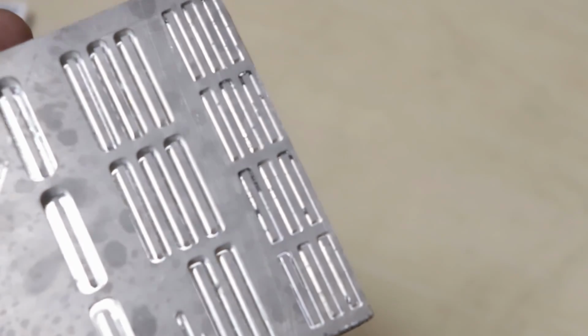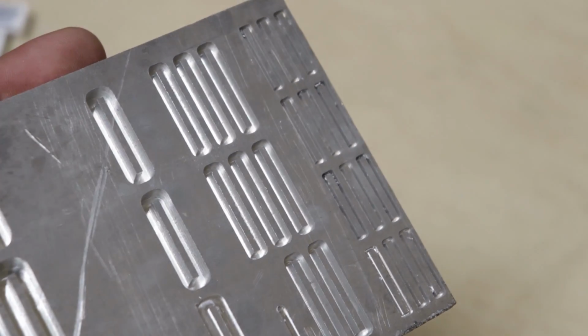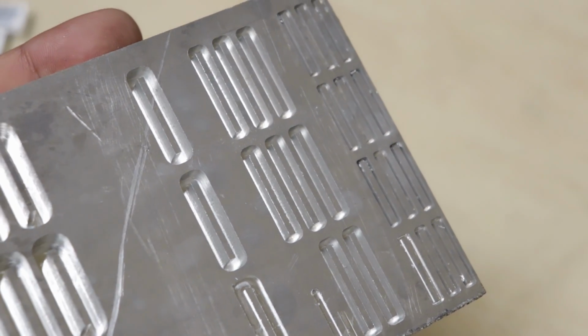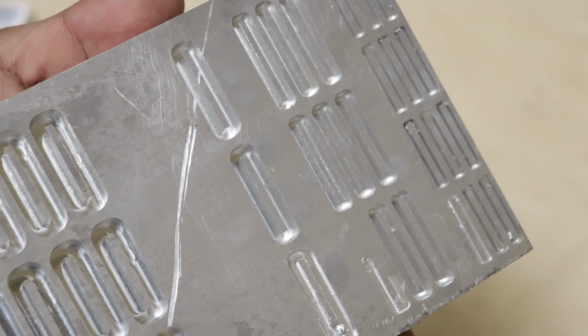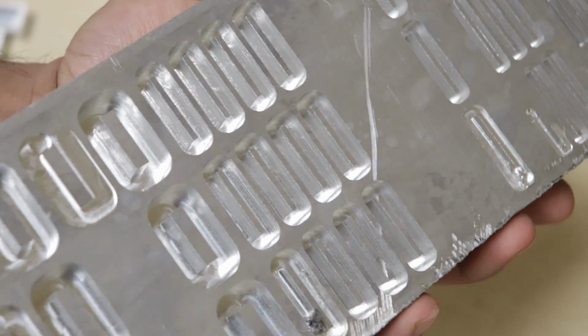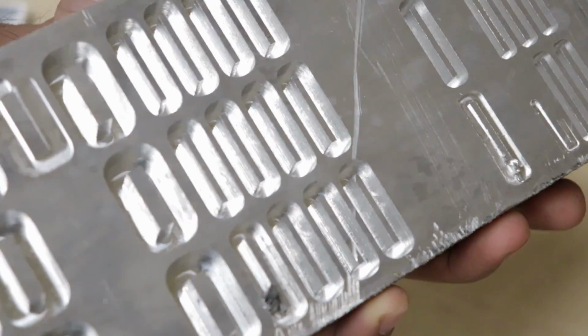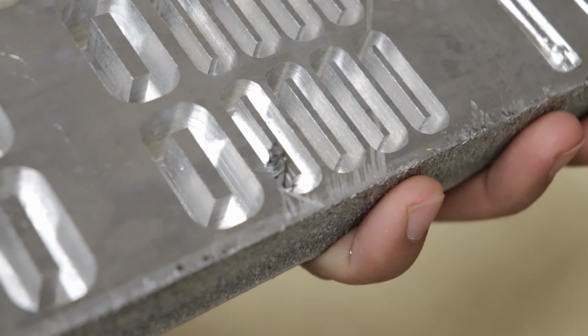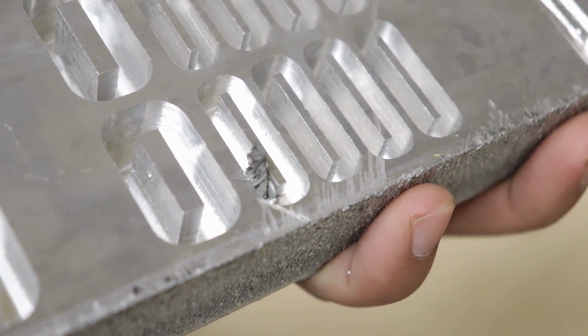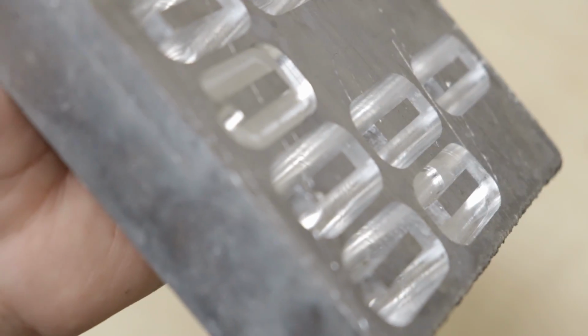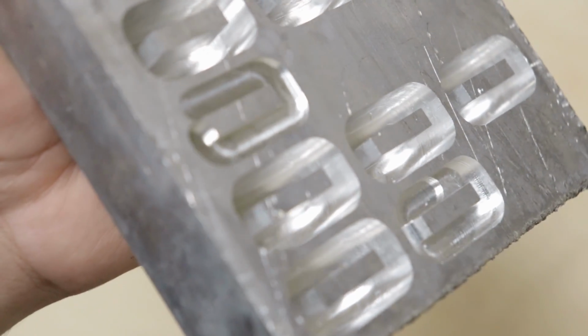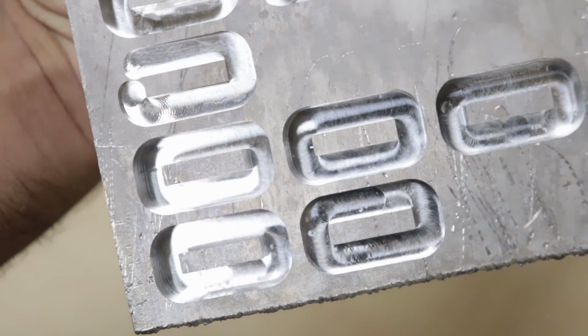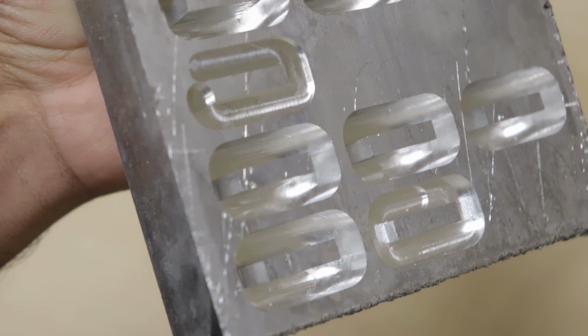Here's that entire chunk of material. You can see all of the cuts leading up to breakage all look the same and went very well. No chatter or bouncing is visible in the walls of the cut. The 4mm tool looks like it actually gummed up with aluminum and broke because of that, which is a sign that things were getting too hot despite having flood coolant. You can also see where I e-stopped on the 6mm cut and how aggressive the ramp down was at that speed.